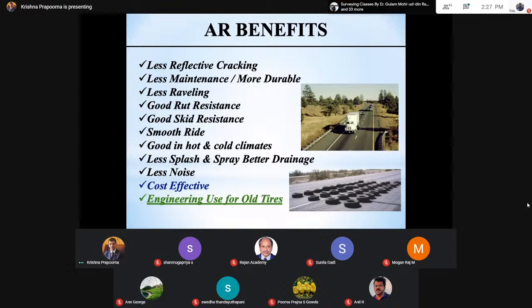So benefits, humongous amount of benefits. You can see multitude benefits here. Reflection cracking, or reflective cracking, what we call. We have the concrete in the bottom. There are cracks near the joints. Obviously, joints are vulnerable to cracks. You have an asphalt overlay. It simply goes up. Now, if you put asphalt rubber as a stress absorbing membrane interlayer, it can arrest cracks. Less maintenance, I told you, more durable, obviously.